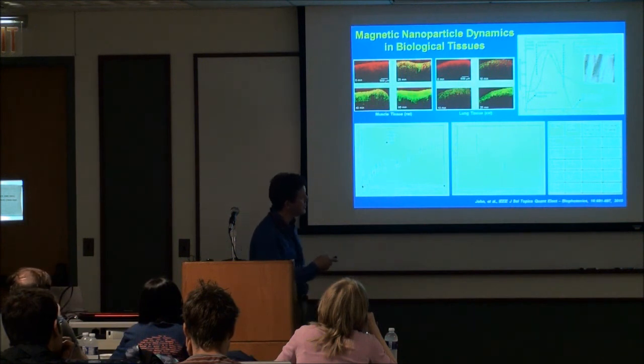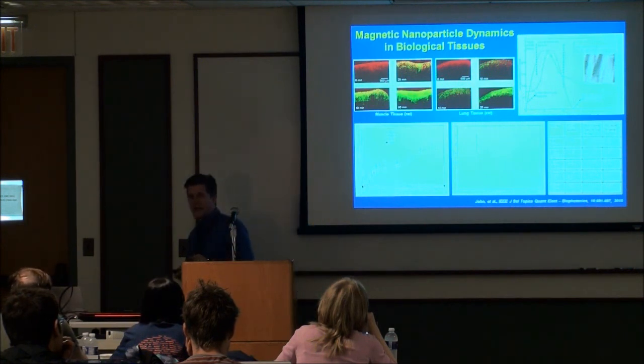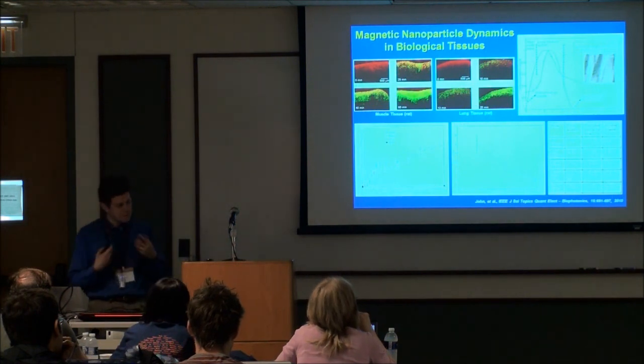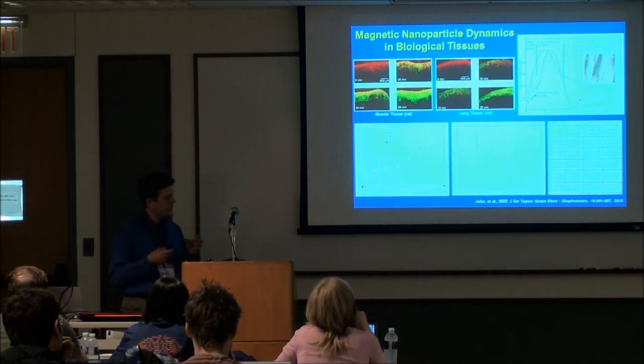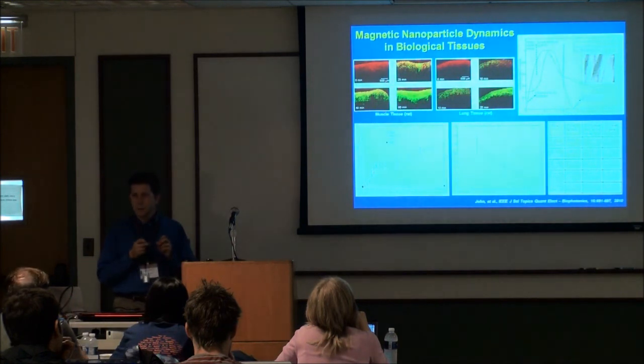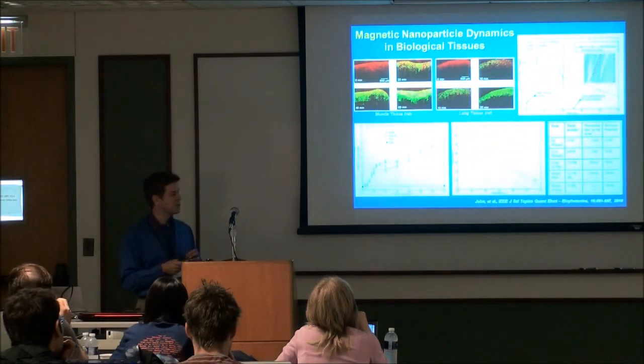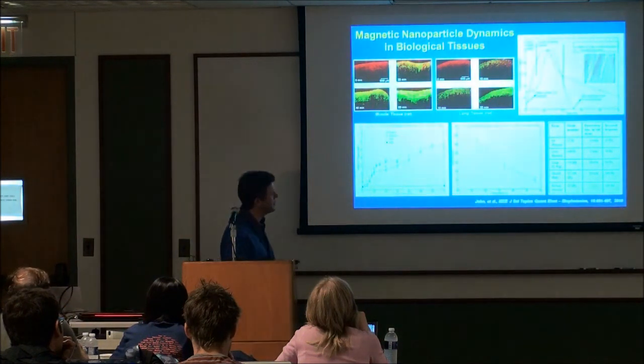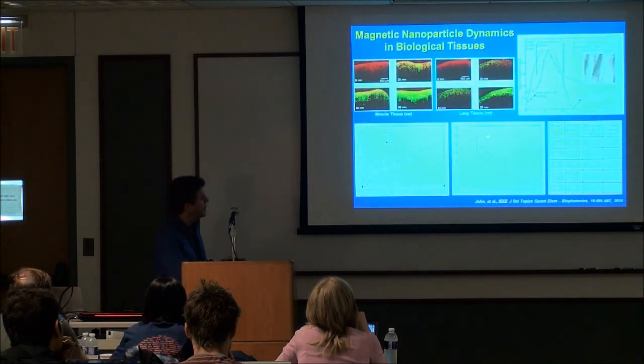And it never quite went to zero because, again, we're looking at nanometer displacements. We hypothesized that even though the bulk material is rock hard, there are little micro cavities of perhaps gel that hadn't solidified, and we're still allowing these particles to move. But we started to better understand how these particles are behaving in tissue.